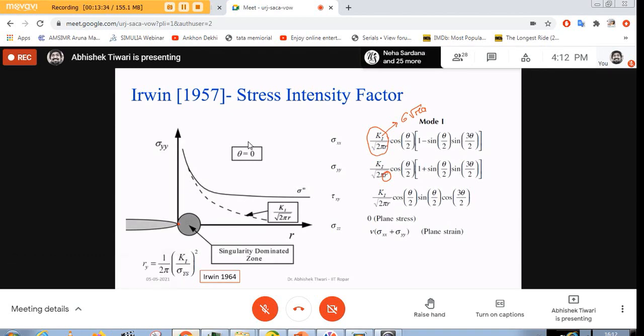That means material is taking infinite amount of load, and if that is true, then we can fight gods, because material cannot break because it is able to take infinite amount of load. But that is not true, because somewhere it will hit the plasticity. And if we assume ideal plasticity, then stress will not increase beyond yield strength. And therefore, there is a small zone, small or larger depending upon the condition, at the crack tip which is deforming plastically.